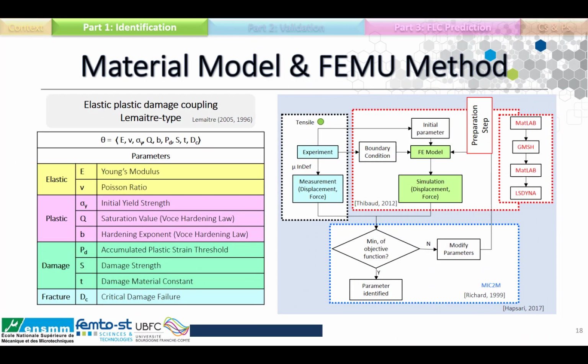So the material model chosen for this project is the elastic-plastic damage coupling of Lemaitre, which consists of 9 parameters, as we can see in this table. 2 parameters for the elastic behavior, 3 parameters for the plastic behavior, 3 for the damage behavior, and 1 for fracture. So these parameters will be identified by using the micro-INDEF test.